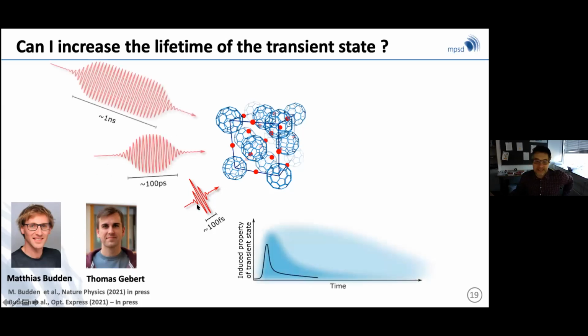If I can take a pulse and instead of making it 100 femtoseconds, I can make it a nanosecond, and if I'm lucky enough that I don't evaporate the whole material because the total energy of this pulse can be kept low enough, maybe I'll be able to stabilize this state for long enough that I can measure with other means, and also look at rigidity of the system at long times. So what we need is a mid-infrared pulse that has a lot of power, around 10 microns, turns out, and that can be used for these pulses.